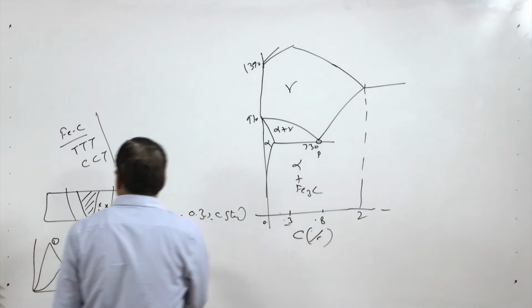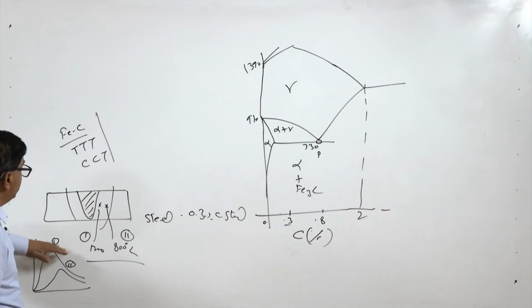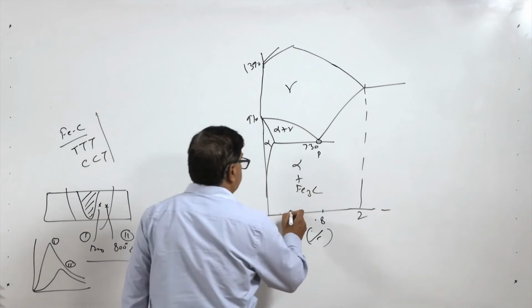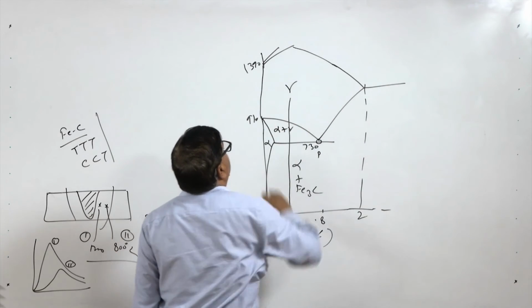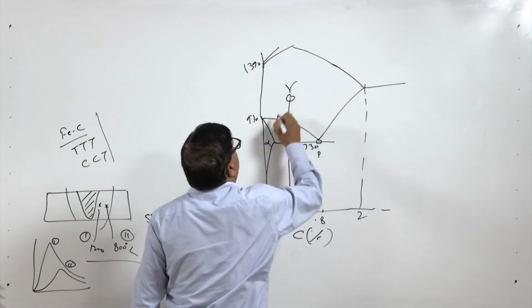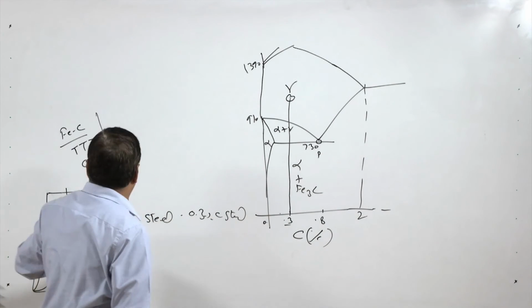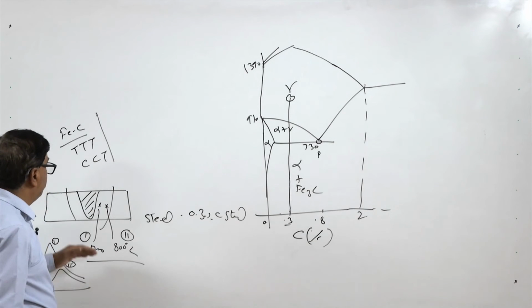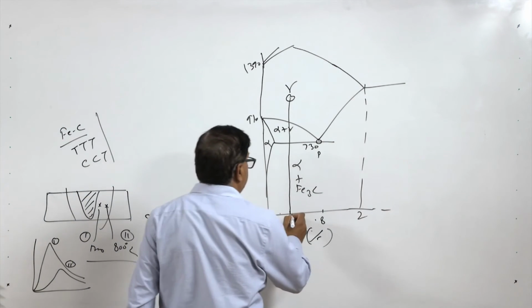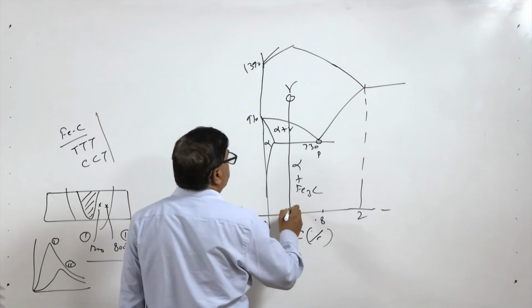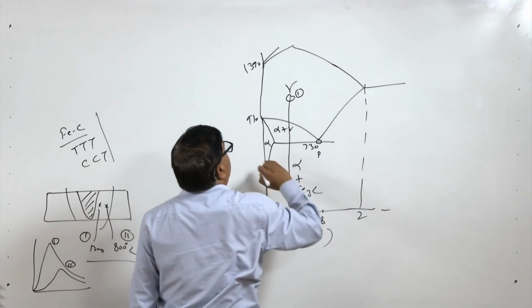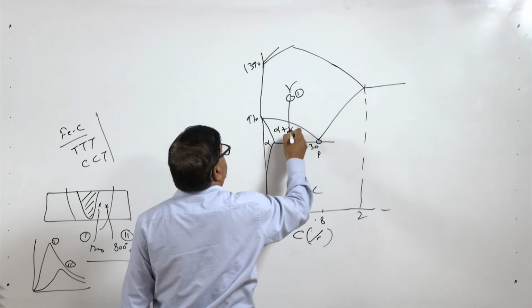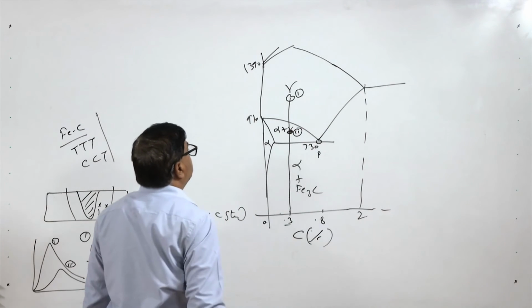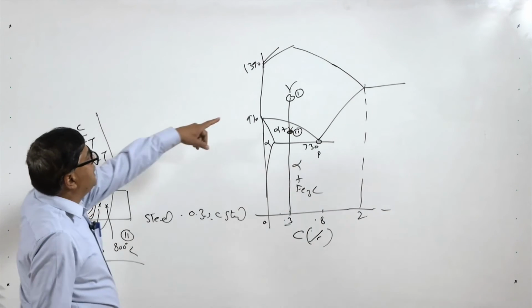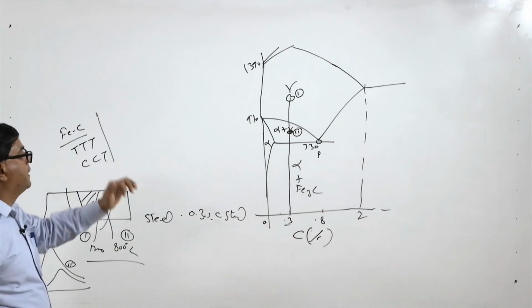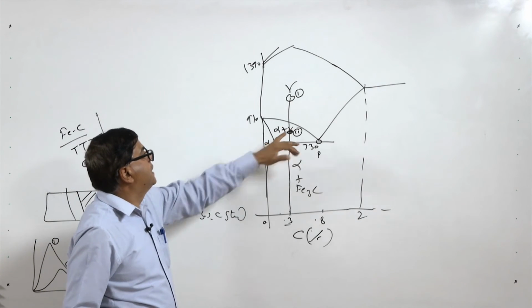So, when point 1 is heated, say up to 1200 degree centigrade, it will experience the changes like this. Here the point will be subjected to the austenitic state, and the cooling rates are quite high as compared to point 2. Point 2 will be heated to the two phase zone, like say this is the maximum temperature for point 2. So, point 1 is being heated to a much higher temperature for a longer period, while point 2 is being heated just up to 800 degree centigrade for a shorter period.